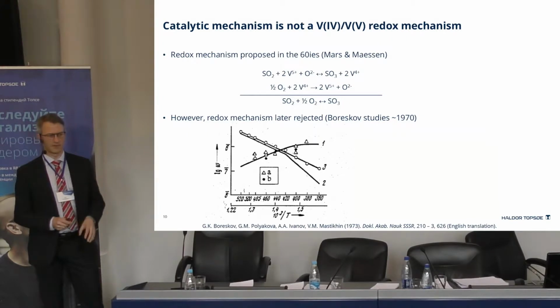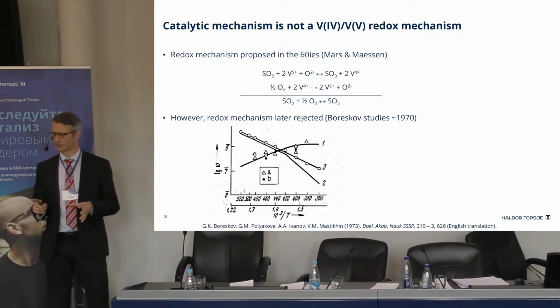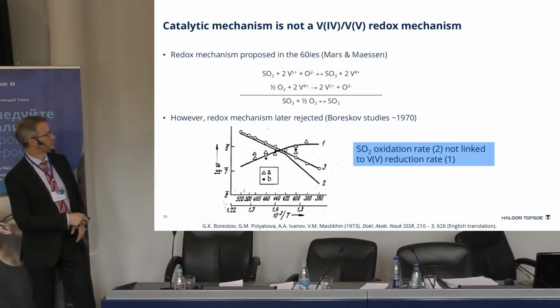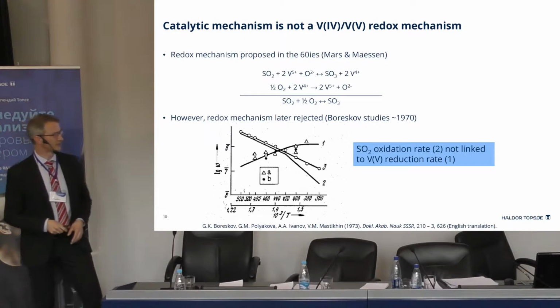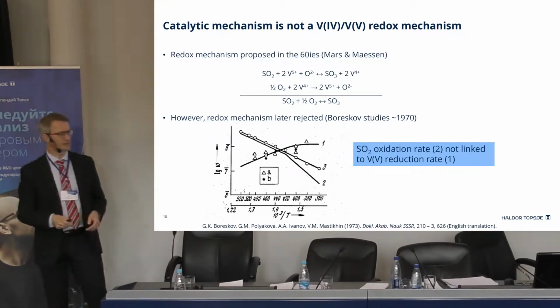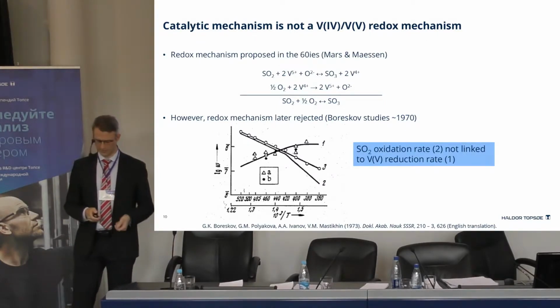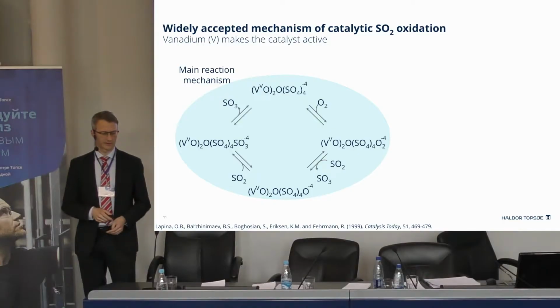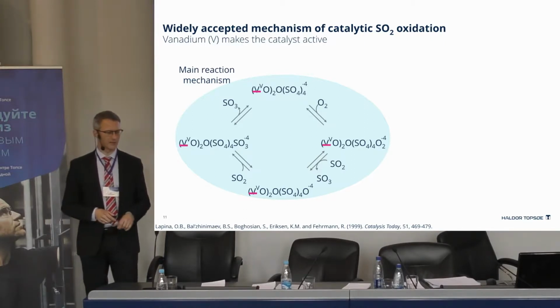And here's one example of how they could show from transient kinetic studies and magnetic resonance techniques that this could not be the case. So here we can see curve 2, that's the rate of SO2 oxidation, and curve 1, that's the rate of vanadium 5 reduction. But if this was the mechanism, they should be equal, and you can see they're not at all. So this could not be the case, and instead it was proposed that the main mechanism was an associative cycle, which is widely accepted today, shown here in a simplified form. So in this catalytic cycle, you can see that all the active species are based on vanadium in oxidation state 5, and they are dimeric vanadium oxosulfato complexes forming the catalytic cycle.